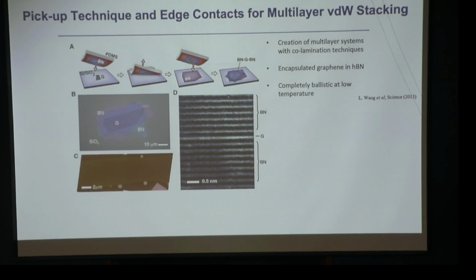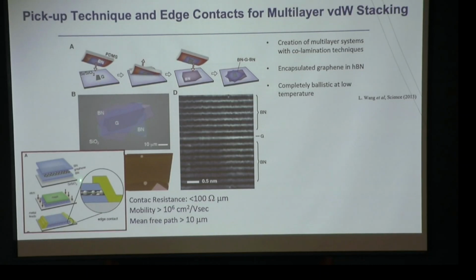If you cut through the sample and look at this interface, you see that this interface is extremely clean. And you see that these TEM images very much mimic what I mentioned in the beginning about how much controllability we can have in getting semiconductor heterostructures, except that this is not necessarily a semiconductor; here an insulator encapsulates the graphene. This technique has evolved in such a way that not only can you stack the layers together, you can also apply microfabrication techniques, such that you can etch part of the crystal and make the contact on the side of the encapsulation in a very different way.